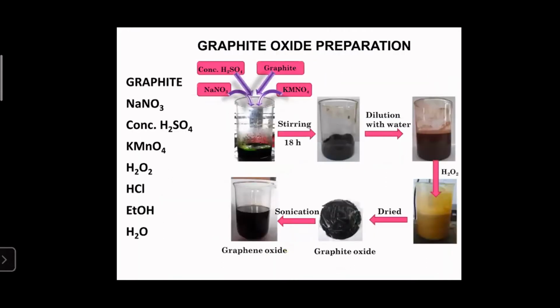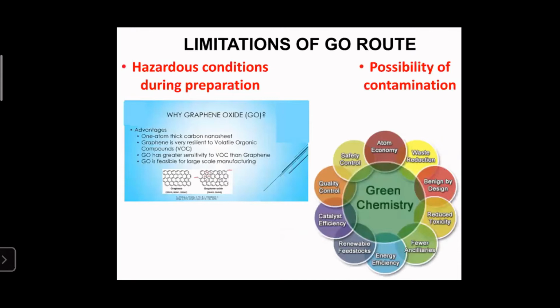These are the photographs during the preparation of graphite oxide. We are using concentrated sulfuric acid, graphite, KMnO4, NaNO3, etc. And it's a time-consuming process. Even though we are conducting the experiment at low temperatures, there are lots of fumes evolving during the experiment. So it is not a green method. So we prefer the preparation of graphene via green techniques, and that's why we call it green graphene. The limitations of graphite oxide assisted methods are the hazardous conditions we are using during preparation and the possibility of contamination. Many graphene oxides possess manganese as one of the contaminants. We are using KMnO4 during the preparation.